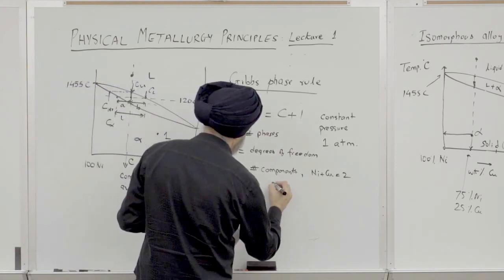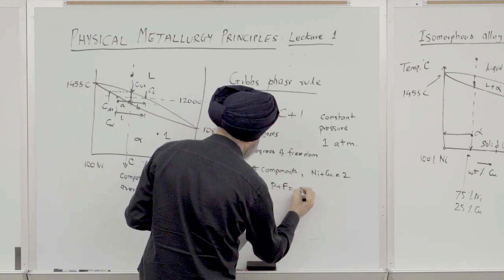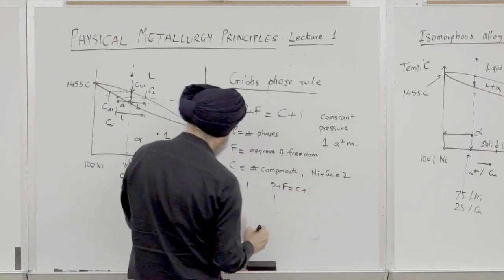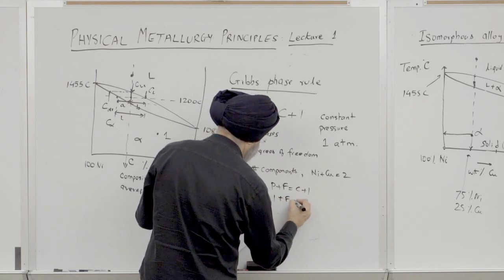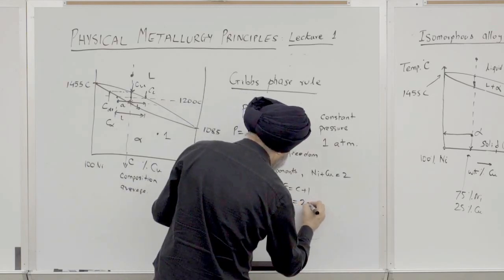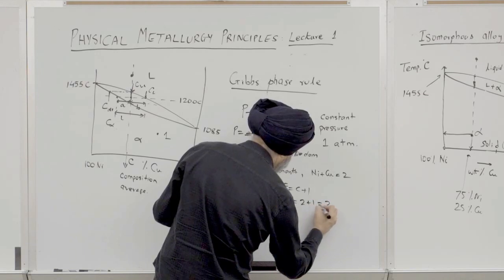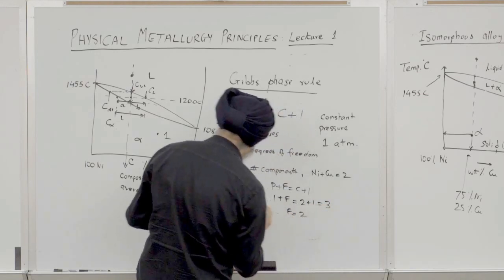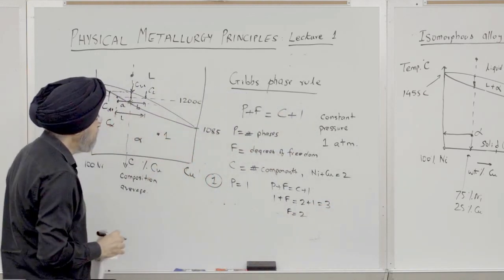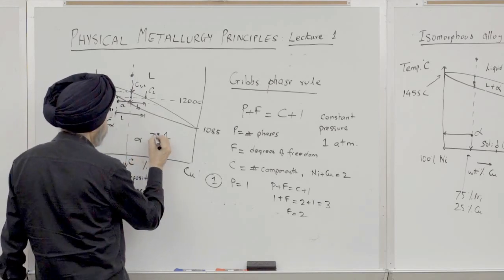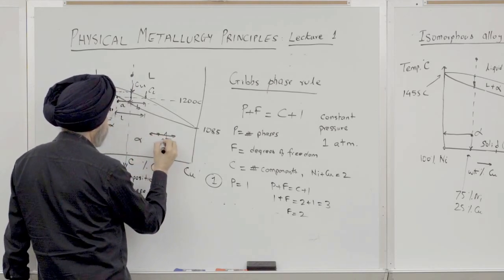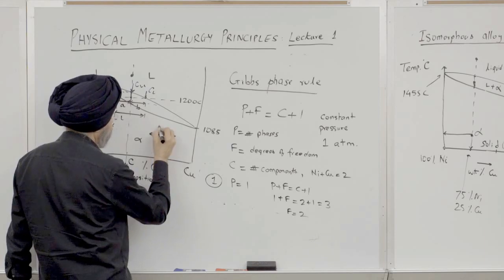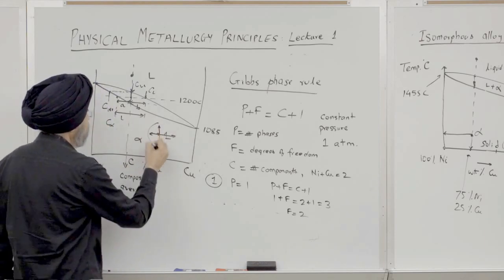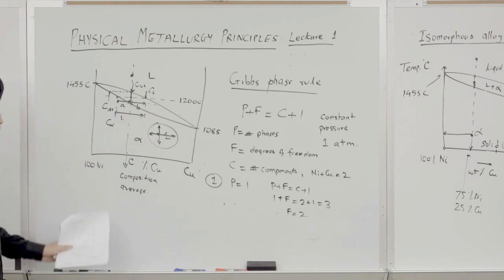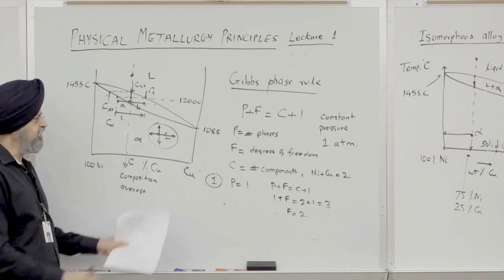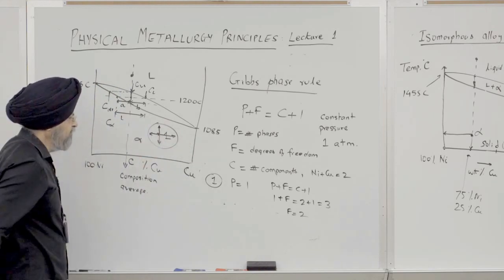So we have P plus F is equal to C plus 1. The number of phases is 1. Degrees of freedom we would like to know. C is 2, so F is equal to 2 for this point here. What that means is I can vary the temperature and the composition, and I'm still in the same region. So I have 2 degrees of freedom, temperature and composition.